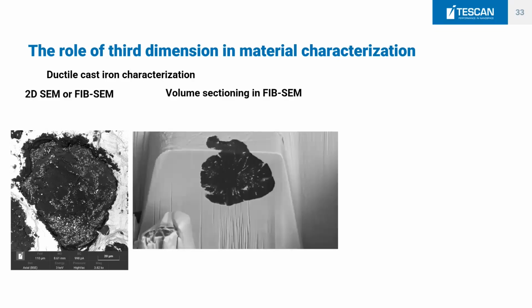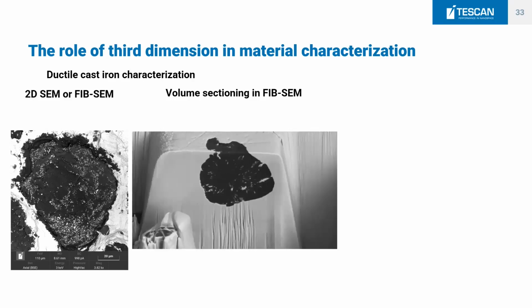But if you use the focused ion beam on exactly the same material, you can make a cross-section of this graphite nodule. And you can see that even the graphite nodule has its own inner structure. It has its own porosity, which you couldn't see when you observe it from the surface. But it also has the dendrite structure and the initiation point where the nodule has been grown.